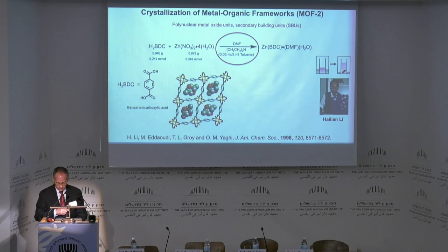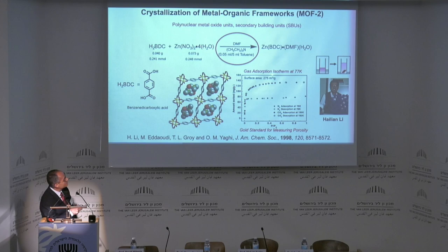And now the question, which the zeolite chemists were hounding me about, was: are they truly porous? To determine whether something is truly porous, you have to do what is called a gas sorption isotherm. There's no other way of doing that. And that's done at 77 Kelvin, it has to be done at 77 Kelvin, and at low pressure.